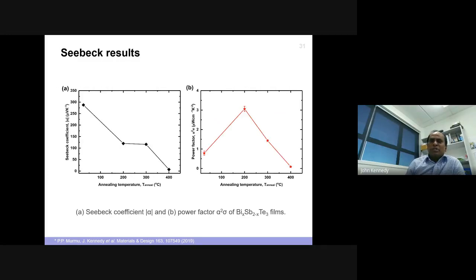Then we looked at, okay, so how does the Seebeck coefficient behave? Because Seebeck is squared, I always look at whether we can really do something with the Seebeck, because then you can increase the efficiency. In this case, you see the as-deposited film has the highest Seebeck coefficient, and with annealing, the Seebeck coefficient went down.